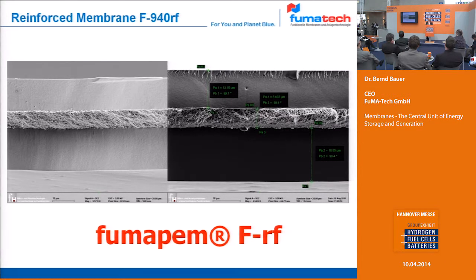If you go into stationary application, you have a safety tool. For us, this is a reinforcement. So all of our membranes, without any exception, if you recommend them for fuel cell application, have a reinforcement inside. Same with our competitors, we know. Everybody is using a different strategy to reinforce. For us, what you see here, we try to have a very thin reinforcement and to allow enough butter coat on both sides of the reinforcement so that you can seriously attach the electrode to the membrane, and that it still allows, even if the backing has some, let's say, erecting fibers, a very low gas crossover and no pinhole creation by erecting fibers.